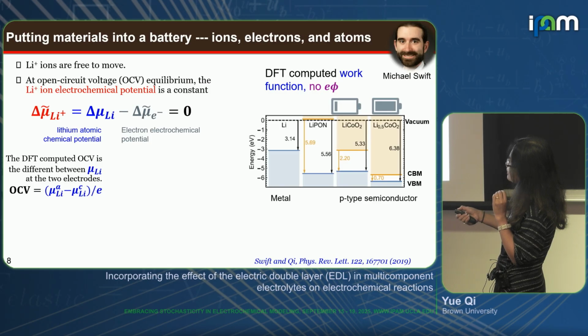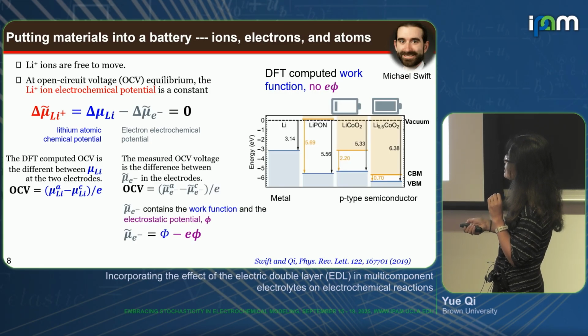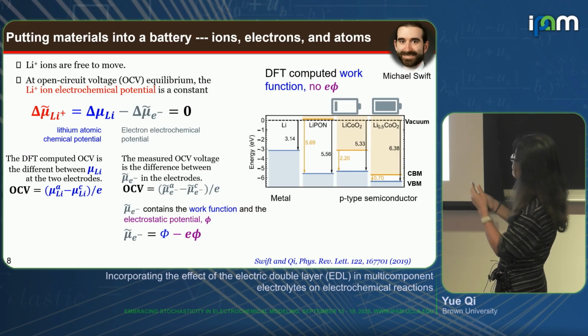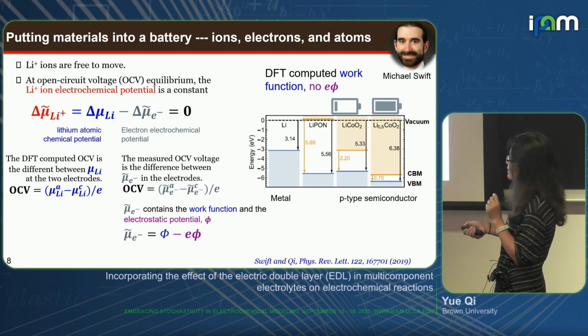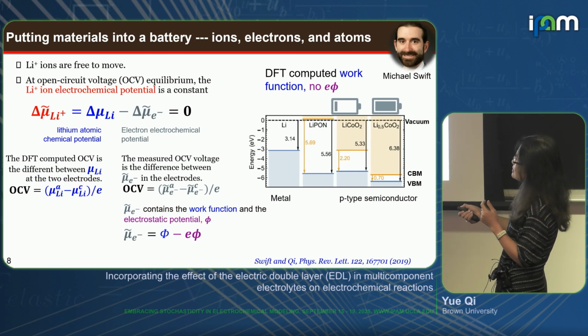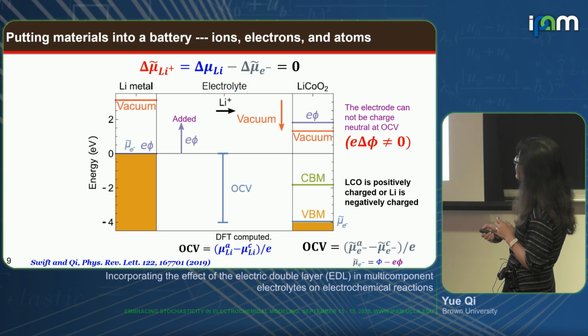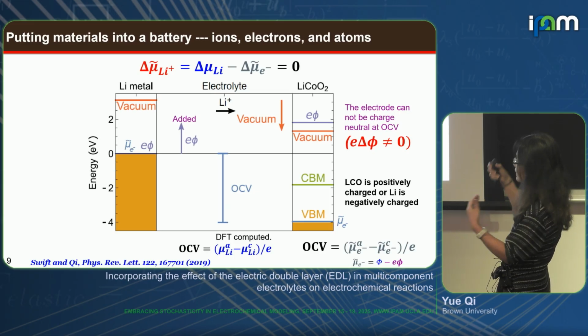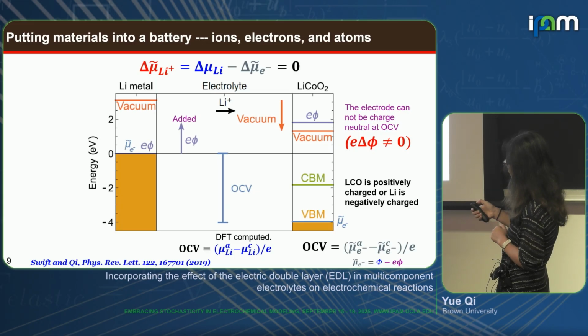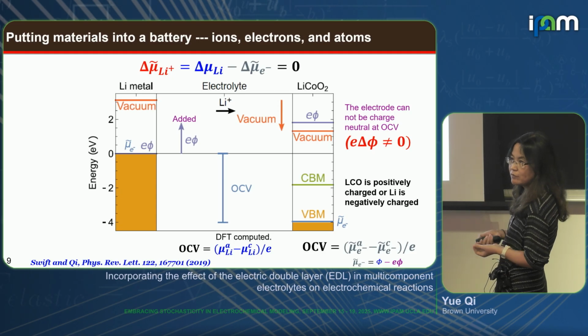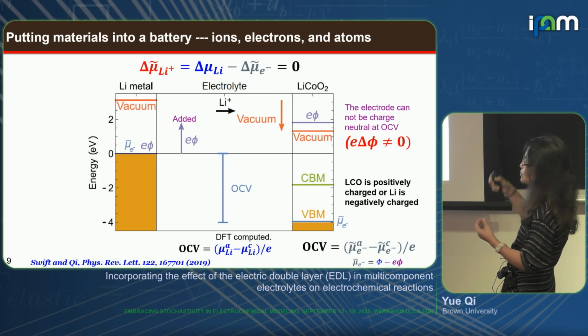We know how. And this one, we know it comes in two parts, right? It contains this work function difference from pristine material and the electrostatic potential, right? So from theory, this needs to be balanced. Therefore, when we connect this in the cell, this needs to change, right? So what's going to happen is we must have a net electric potential difference between the electrostatic potential of our cathode and anode materials, and that will shift the electrons' electrochemical potential level to be equal to the open circuit voltage, and that's the 4 volt. Right? So here we can estimate the difference of the two.